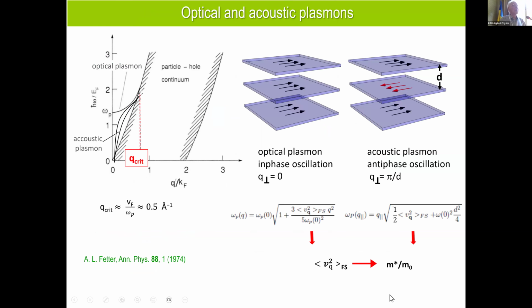When you have layered systems, and you have a momentum perpendicular to the layers, you can get anti-phase oscillation, and when you have a movement to the right and the left, then you need no energy, and therefore the plasmon energy goes to zero, so you have acoustic plasmons. And in both cases, in the homogeneous systems or in the layered system, you can get information from the dispersion on the Fermi velocity, and then you can get information on the renormalization due to a higher effective mass.